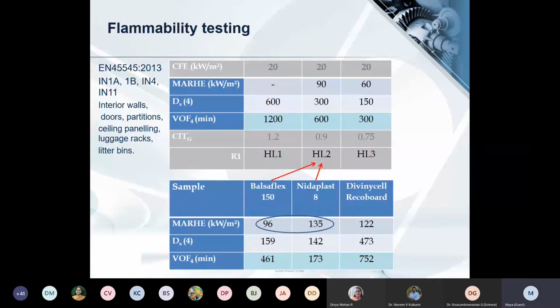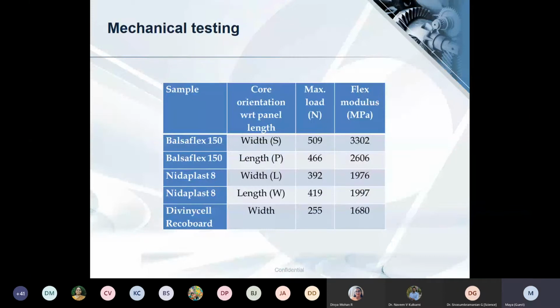Now, this is the mechanical testing of the panels. And again, you can see that the panel containing the balsa core exhibited the highest modulus as well as the maximum load. The maximum load was 509 newtons, while for the panels that we developed for the aerospace sector, the load that was required just needed to be greater than 350.